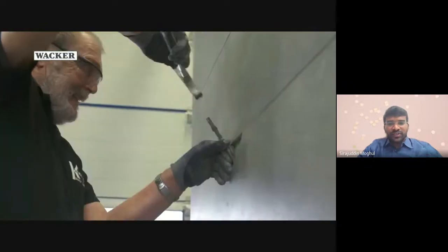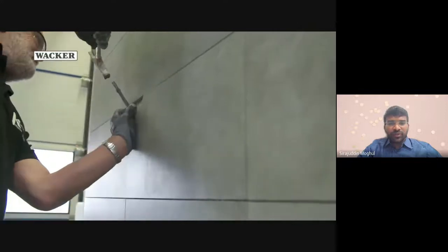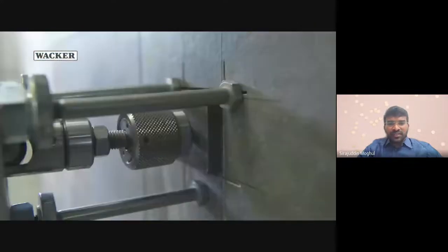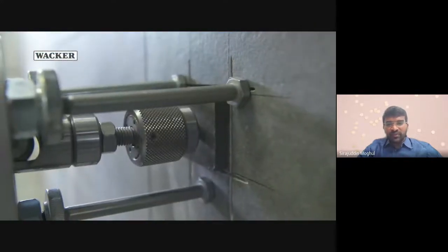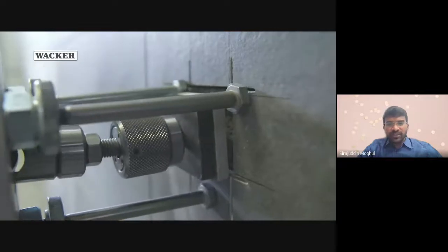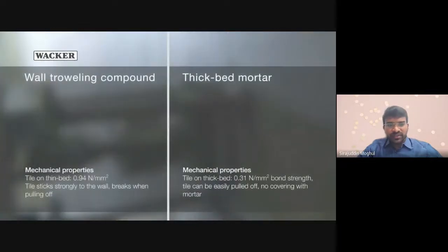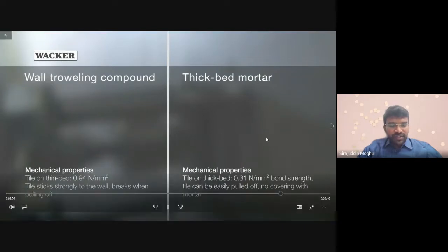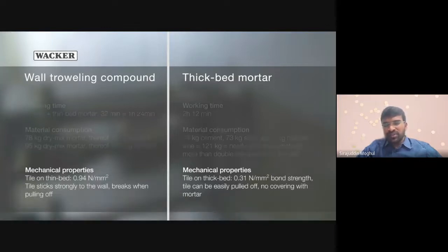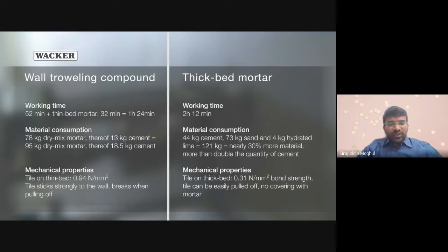And if it is on the thin bed, you won't be able to even remove it because the polymers have such good adhesion that it bonds very well with the wall. So even if you do the tensile adhesion test, if it is polymer modified, we will have a very high tensile adhesion of 0.9. And if it is a thick bed, the adhesion is very minimal, which is 0.2 or 0.3. So you can see the advantages that we get when we use thin bed and thick bed.